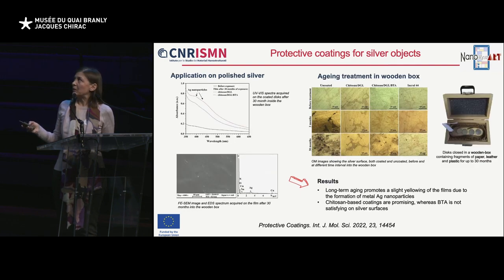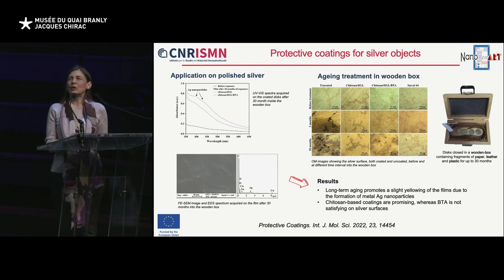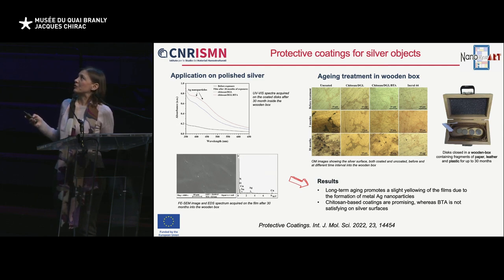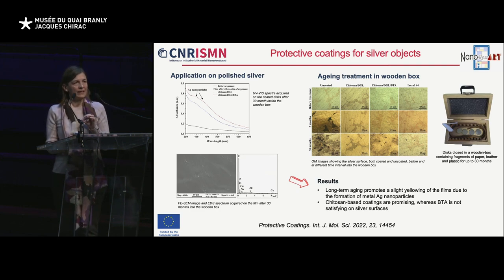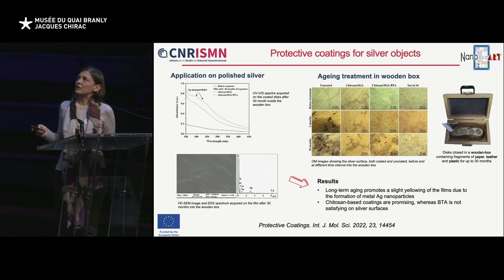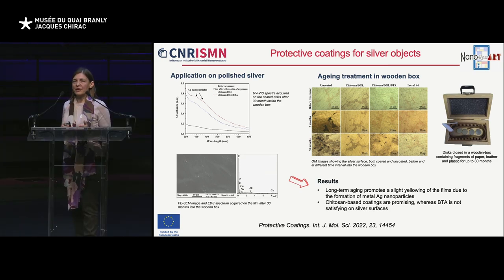So then, in addition to accelerated corrosion treatment, we also performed some aging treatment in a wooden box to promote the degradation, but in a more real-like environment, in the presence of fragments of paper, leather, and plastic. And after 30 months, we observed that the uncoated is degraded just after only 3 months. In the case of the chitosan formulation, we can have a certain protective efficacy, but we observe a slight yellowing of the coating. And by looking at the UV visible spectra, we observe the presence of some signals which are compatible with the presence of silver nanoparticles, and this was confirmed by scanning electron microscopy.